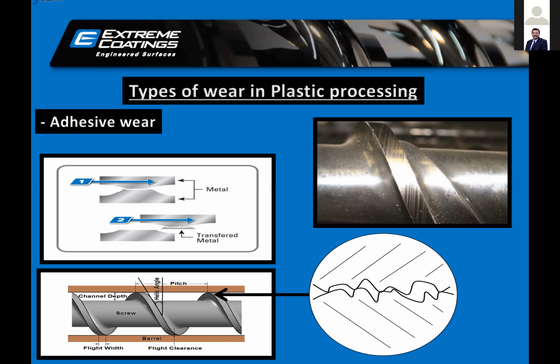If you see specifically in most of the systems, the wear starts at the metering zone, because that's the area which is more free for movement, and that area is continuously in touch with the barrel, and it starts getting ruptured from that end. So in all of these systems, be it injection molding or extrusion, small screws or big screws, this adhesive wear is always there in the system.